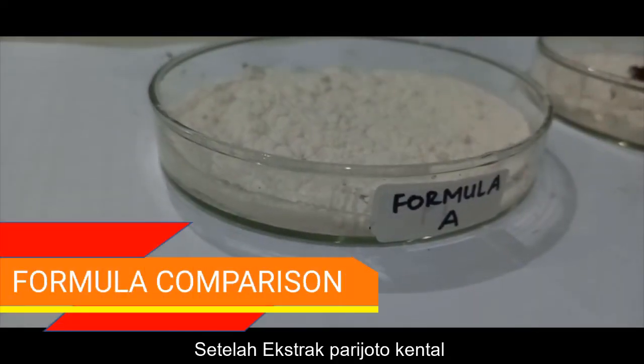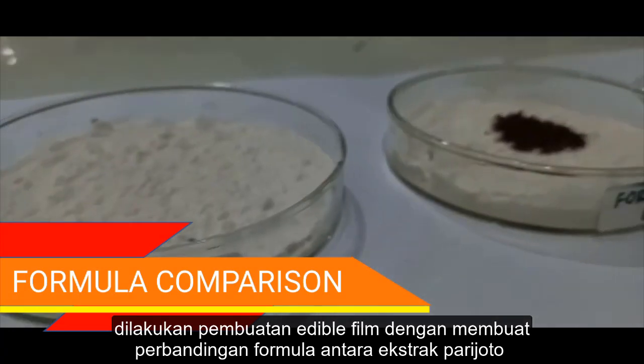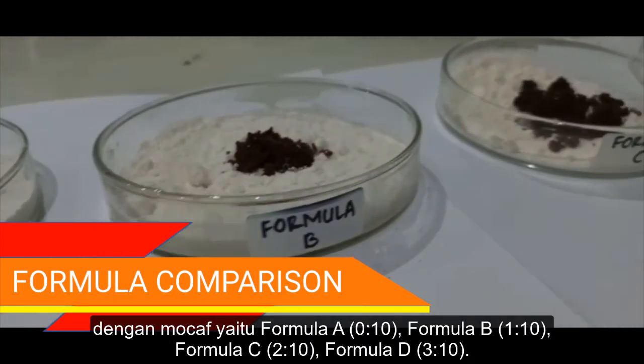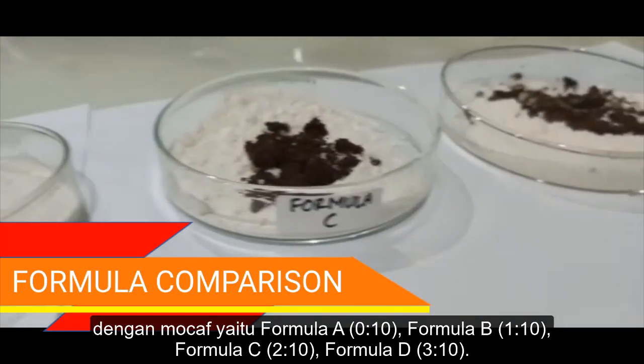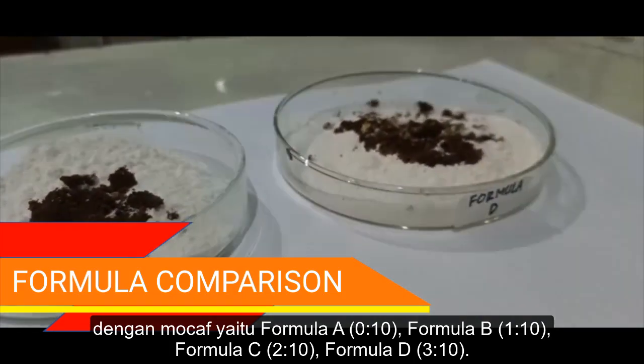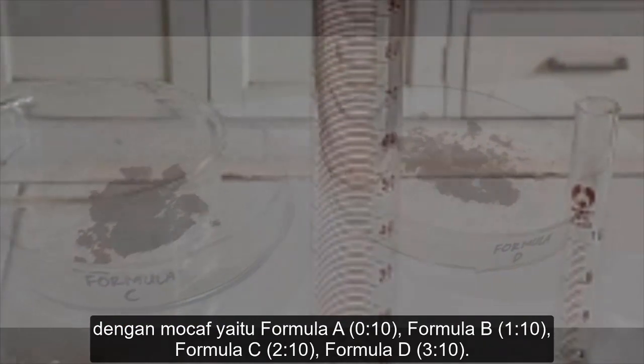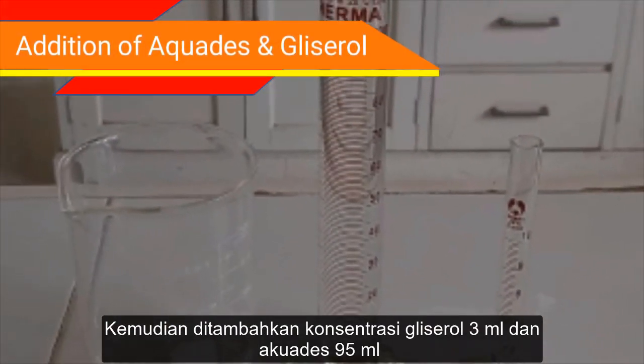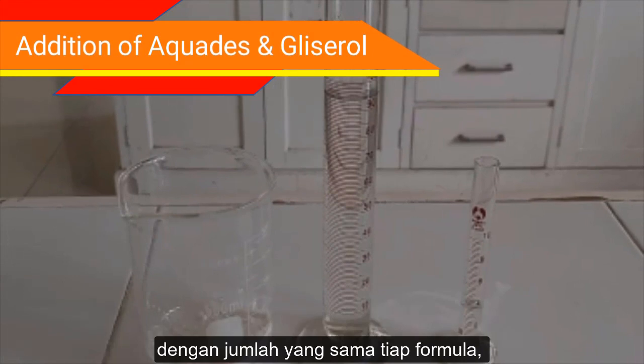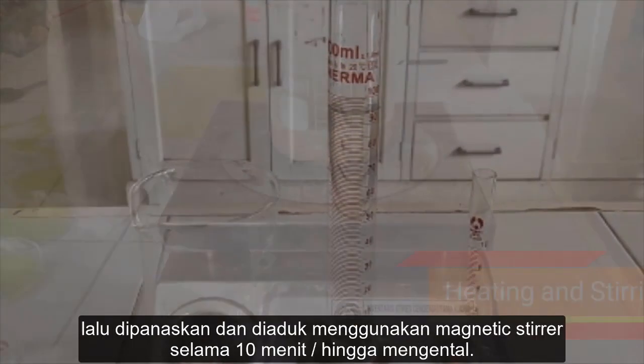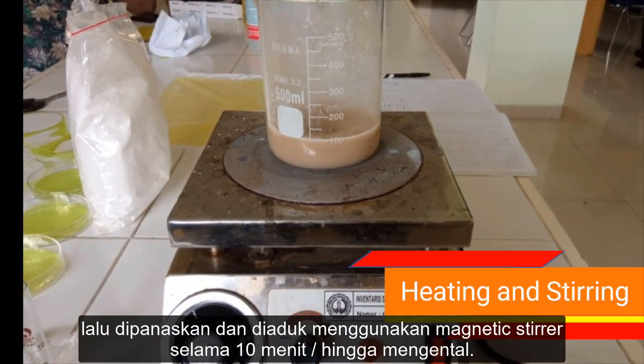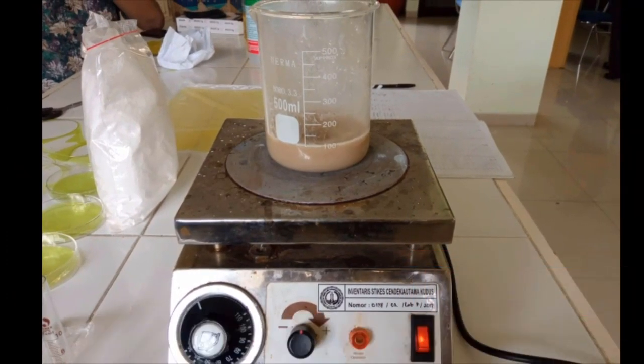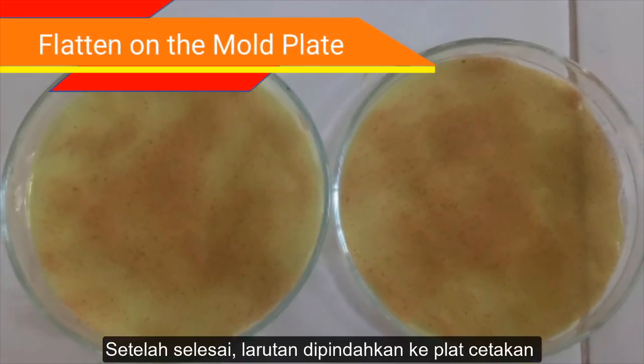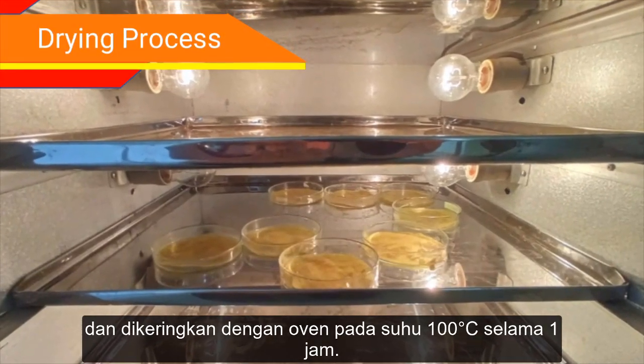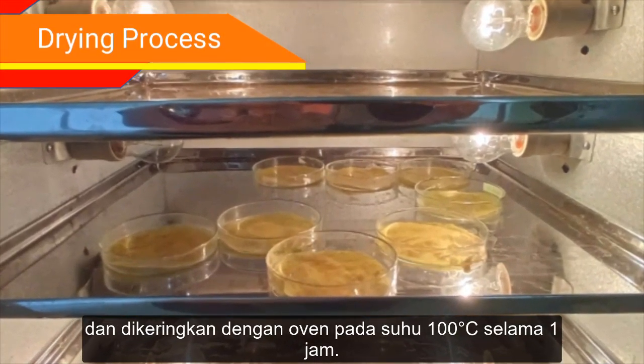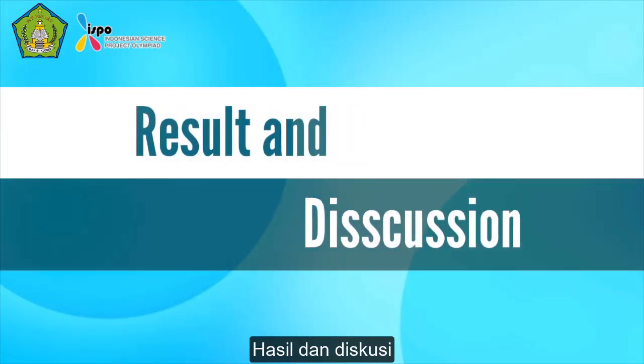After the parijoto extracts turned thick, we compared the formula between parijoto extracts and mocaf. Those are formula A 0 to 10, formula B 1 to 10, formula C 2 to 10, formula D 3 to 10, then 3 ml of glycerol concentration and 95 ml of aquades with the same amount for each formula, then heated and stirred using a magnetic stirrer for 10 minutes or until thickened. The solution was transferred to a mold plate and dried in an oven at temperature of 100 degrees Celsius for 1 hour. Result and discussion.